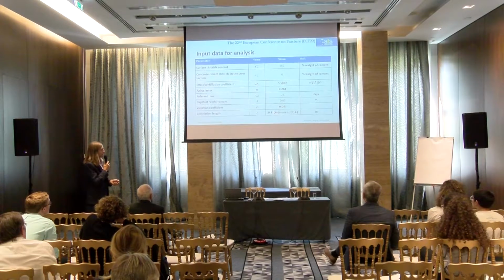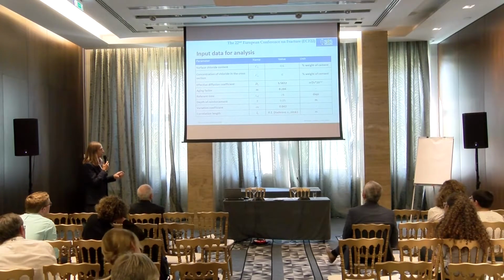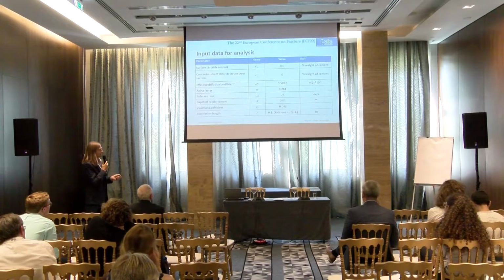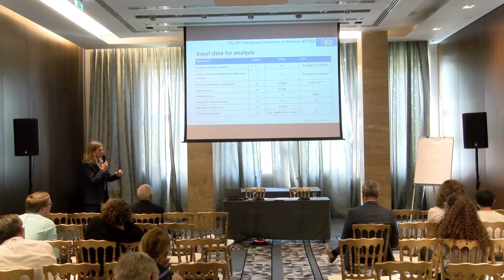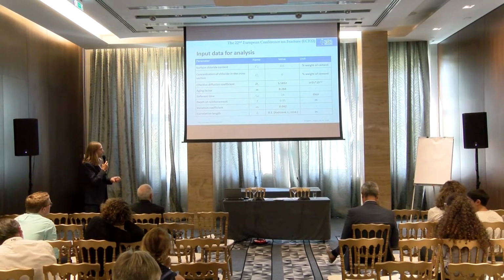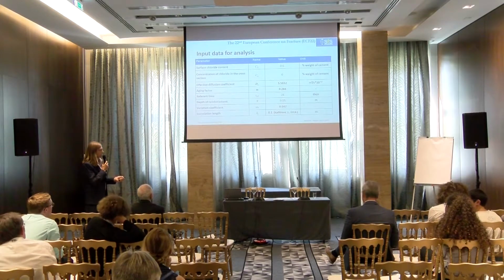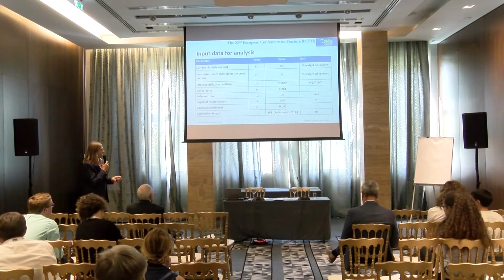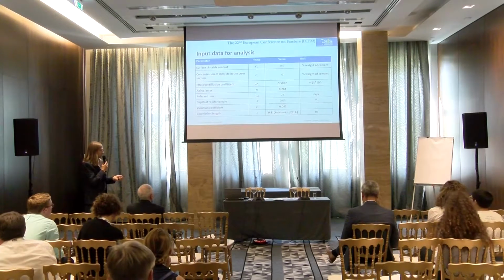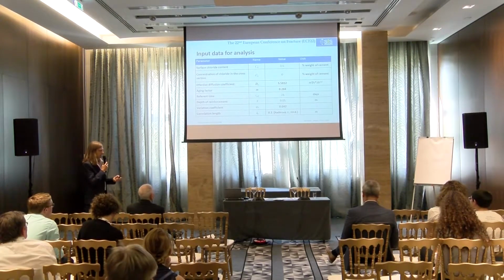Here are the random input parameters. So the material property is the diffusion coefficient. Since concrete improves its property over the age, over the time, due to the chemical process of hydration, here's the aging factor, and the variation coefficient of the material property is given here. And what is most important, the correlation length that controls the spatial variation was adopted based on the suggestion here.